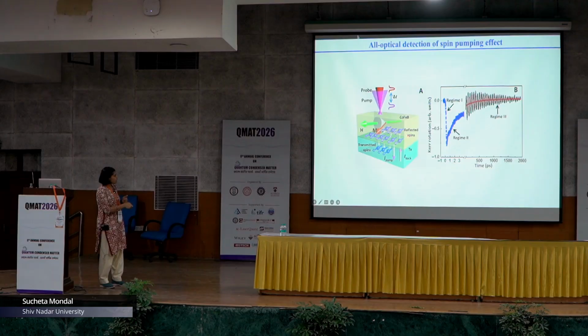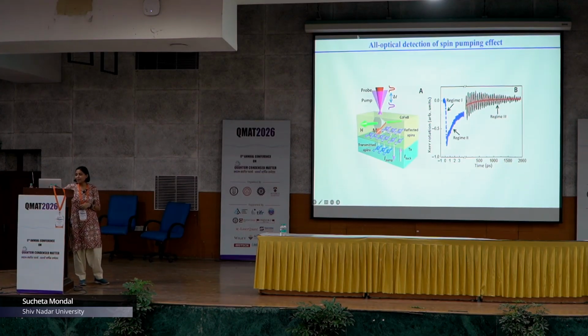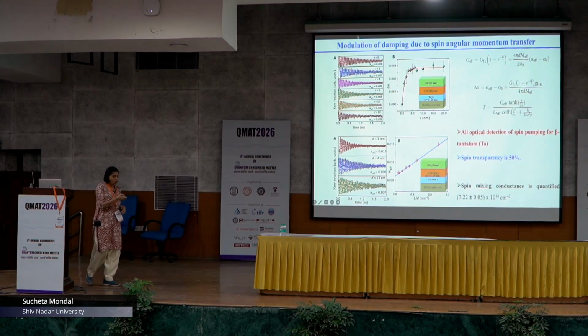Because of this transfer of angular momentum, there is a transfer of spins, which is also diffusing according to the diffusion length of the material. There could also be backflow depending on the thickness of the layers. So this phenomenon is studied varying both the cobalt-gadolinium layer thickness and the tantalum layer thickness to verify certain parameters. What are those interesting parameters? Like in the previous talk, we came across a question: what is the role of the interface, whether it is transparent and allows the spins to flow easily to the other layer or be detected easily.